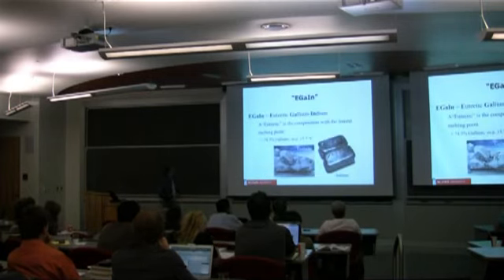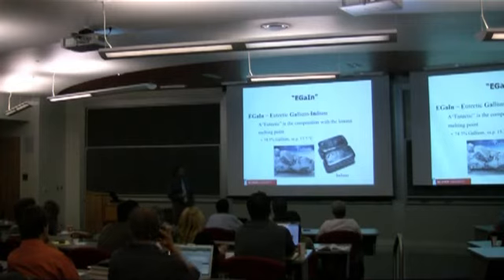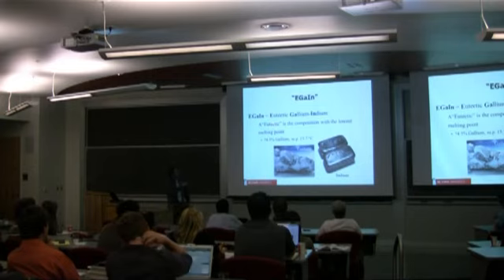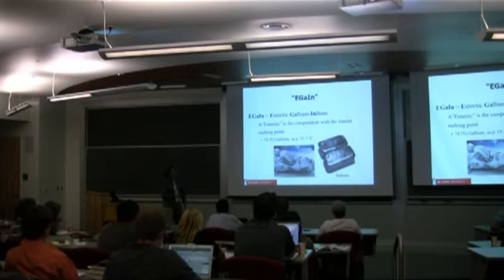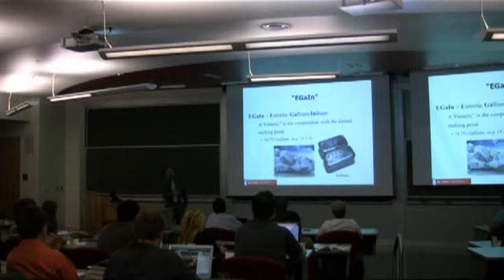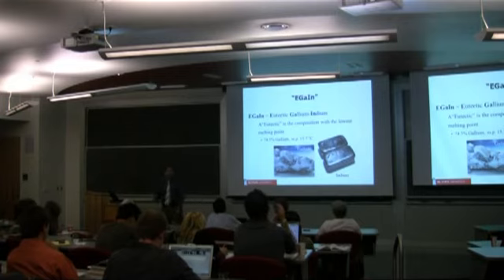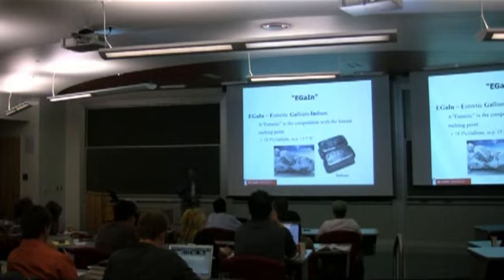Okay, so what is the material? We call it E-gain, and I will try to just refer to it as liquid metal to avoid confusion, but E-gain stands for eutectic gallium and indium. These are just things you can buy off the shelf, so it's not really a new material, it's the way that we're studying it. The reason that we use a mixture of gallium and indium is that gallium by itself, which is really the material we care about, melts at 30 degrees Celsius, which is technically a solid at room temperature. By putting in some indium, you depress the melting point to below room temperature, and you therefore have a liquid.